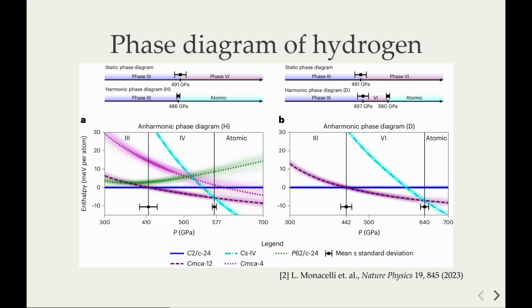So on the top we have the static phase diagram, which means we don't have any phonons at all, just ions in their minimum position of the Born-Oppenheimer energy landscape. We predict hydrogen to go between phase 3 and phase 6, which are a molecular non-superconducting phase, and the atomic phase, which is the gas high temperature superconductor, is not stable before a terapascal, so completely unreachable from an experimental point of view.